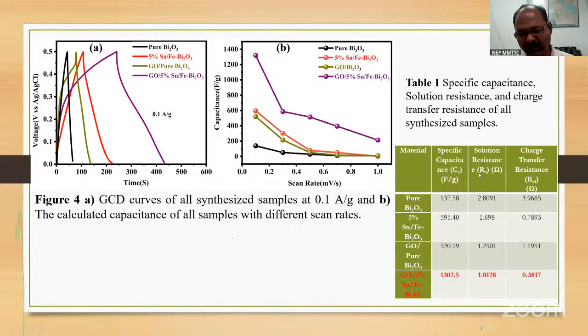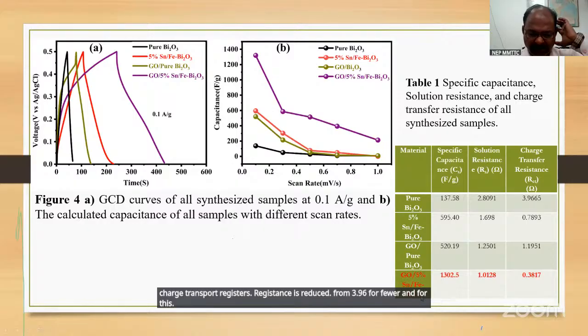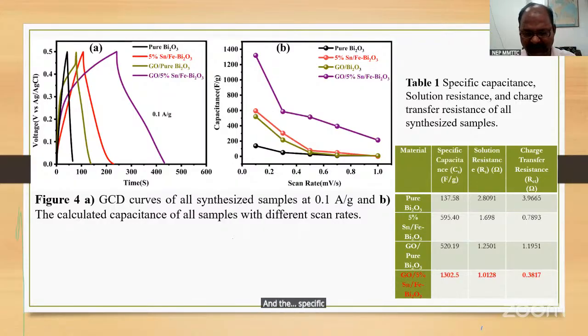The solution resistance, you see here, is decreased, and the charge transfer resistance in ohm, now you see here 0.3, a drastic change. Charge transfer resistance is reduced from 3.96 for the pure sample. And the specific capacitance in farad per gram is enhanced, and this is a notable change which occurs here for this 5%.